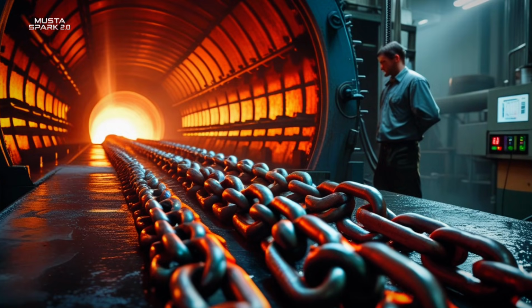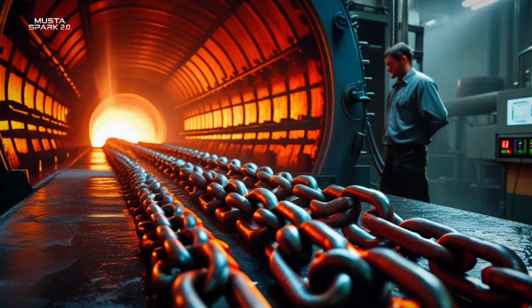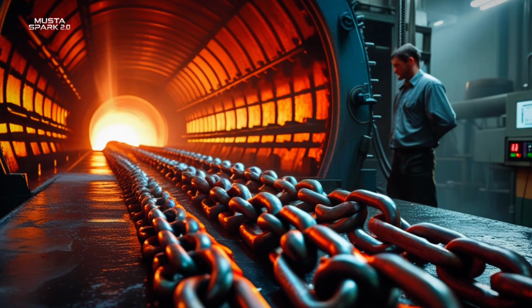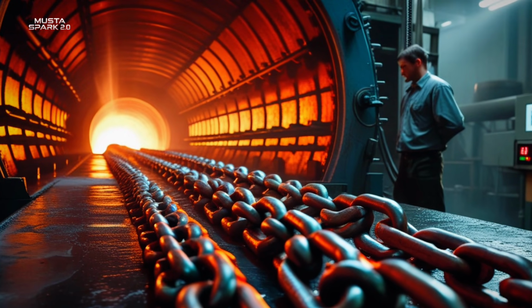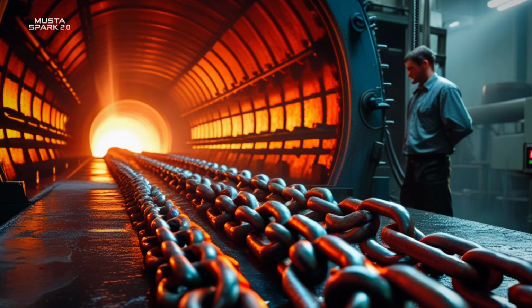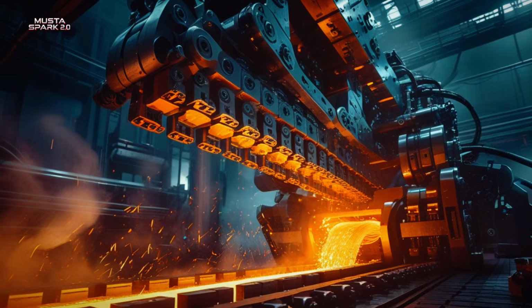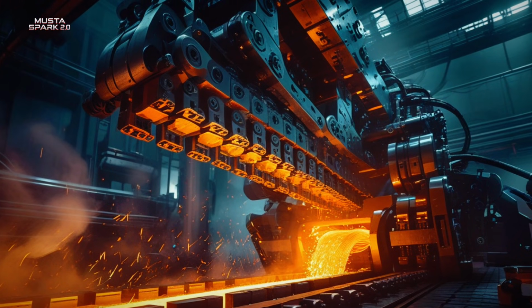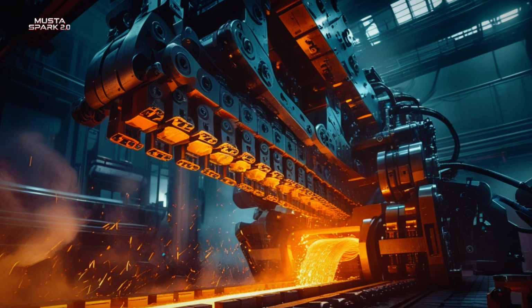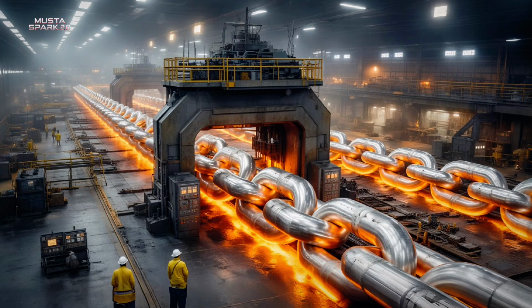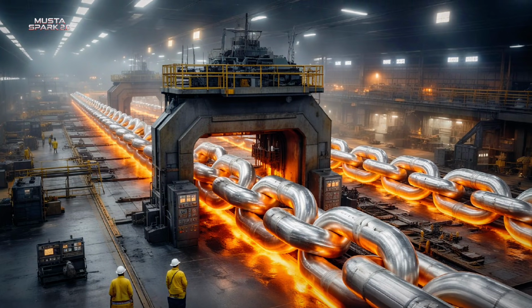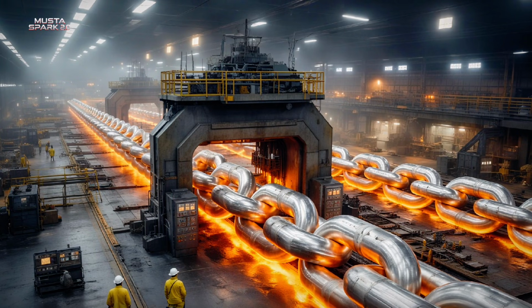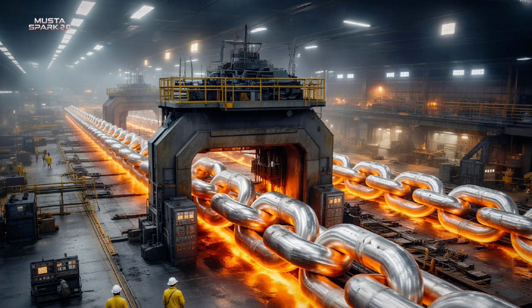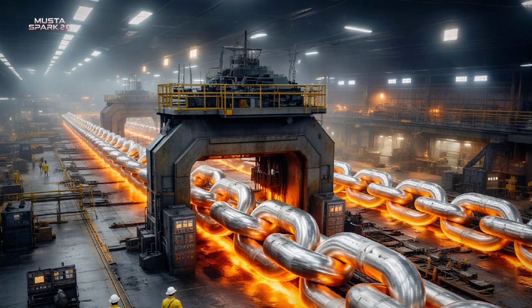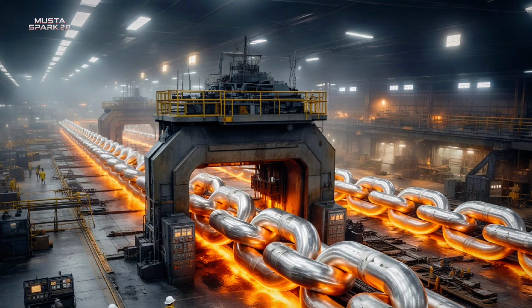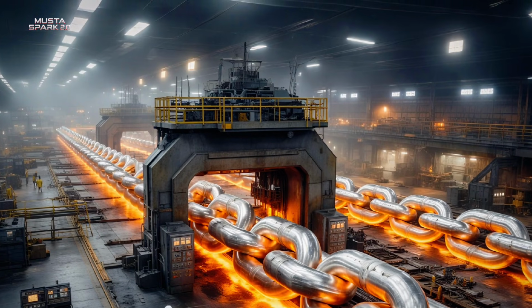Enter tempering. The quenched steel is reheated, this time to a lower temperature, around 500 to 650 degrees Celsius, and held there. This controlled reheat reduces the brittleness while retaining most of the strength gained during quenching. The result is a steel with a carefully balanced combination of strength, toughness, and ductility, the ability to deform slightly under extreme load without fracturing catastrophically.